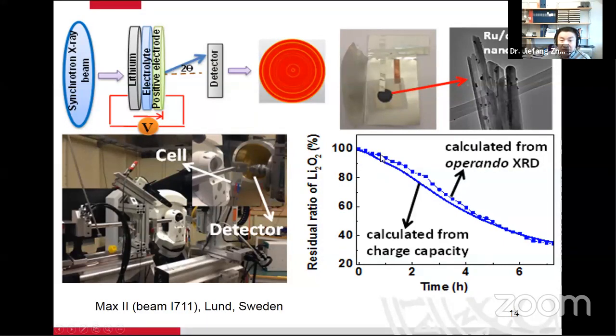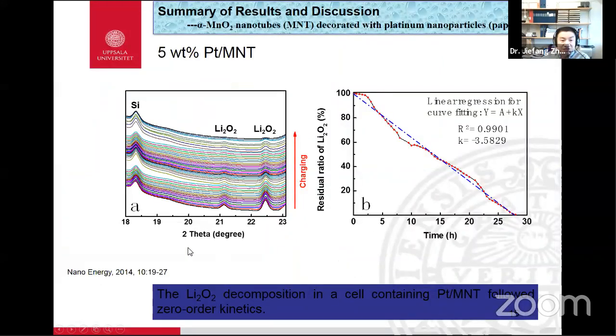So here you get the measured lithium peroxide amount. This is calculated from the XRD result. This you can calculate from the capacity, the real capacity. This is like a theoretical curve. This is the measured data. So this is one example